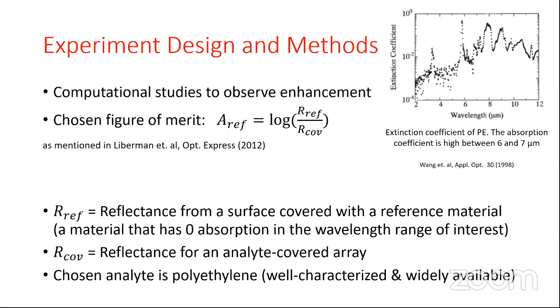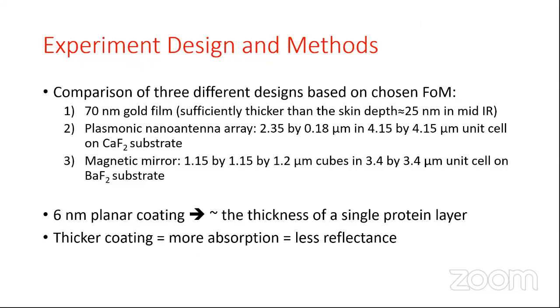And you could see between 6 and 7 micrometers, the extinction coefficient is roughly 2 orders of magnitude. And this is the wavelength range of interest I'd like to shoot for. And in the study, I will be comparing 3 different designs based off the chosen figure of merit. Initial case is a 70 nanometer gold film, which is sufficiently thicker than the skin depth, which corresponds to roughly 25 nanometer in the mid-IR range. So this should not give us any enhancement, but will basically be the baseline for our case.